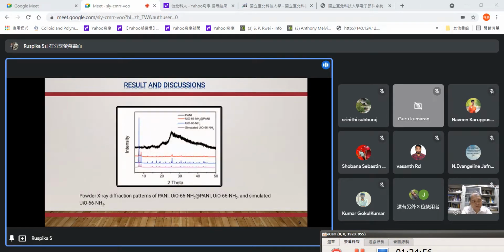This is the XRD pattern of polyaniline. For polyaniline, we got two broad peaks at 20 and 25 degrees, which represent the 100 and 110 planes. For UiO-66-NH2, the XRD pattern matches the calculated XRD pattern, and the final composite displays a similar XRD pattern to UiO-66-NH2 with a slight difference in the peak intensity.